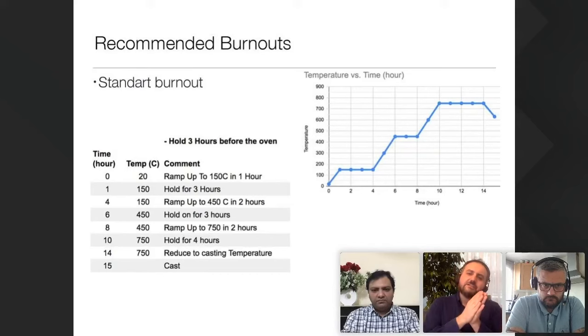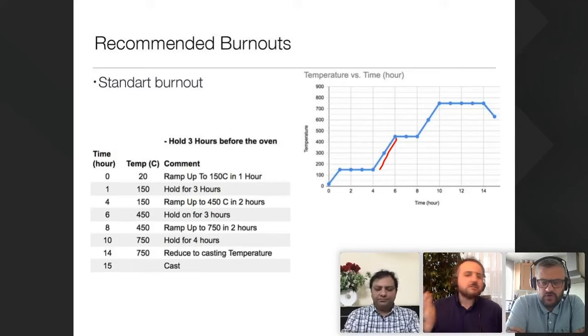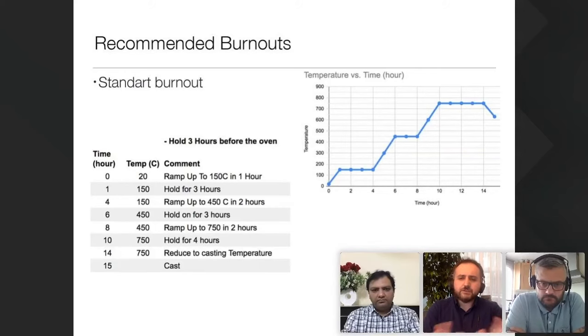So the second step is you ramp up to 450. At that ramping up, at least on this schedule, you don't want to ramp up too fast, because all of our investment powders have an optimum ramp rate of 150 degrees Celsius per hour.